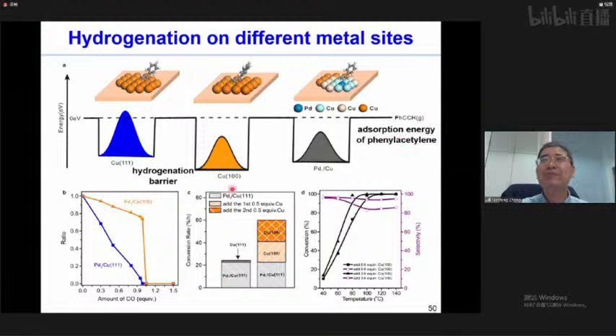And in another experiment, we have this palladium copper (111) catalyst, and then we add additional copper 100, which is not active by itself at all. You see, we add one portion, we increase the activity. Another portion increases the activity again. So which means that the copper 100 is really active for the hydrogenation. Okay, so this is quite interesting. And this phenomenon is also confirmed by carbon monoxide poisoning. You see, when we introduce carbon monoxide, the activity decreases slightly, but the activity completely disappears only after all the palladium gets poisoned.